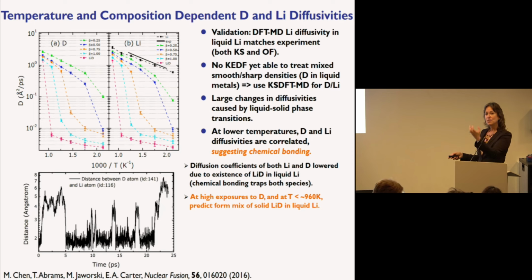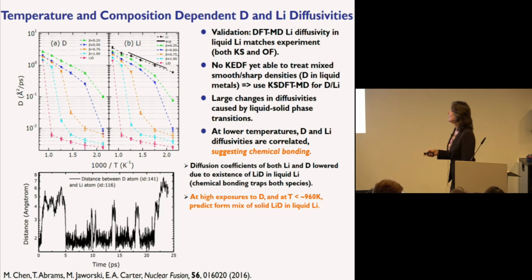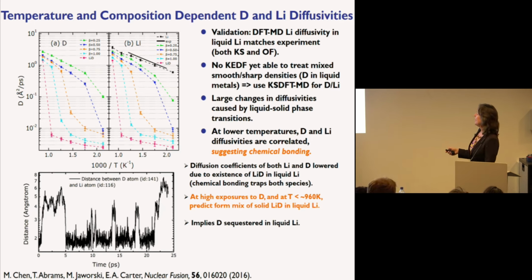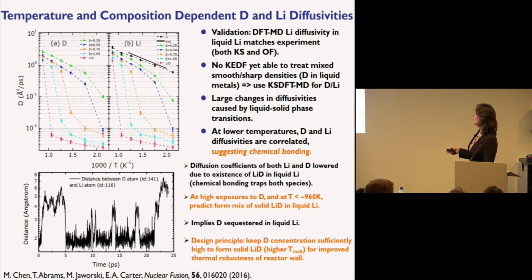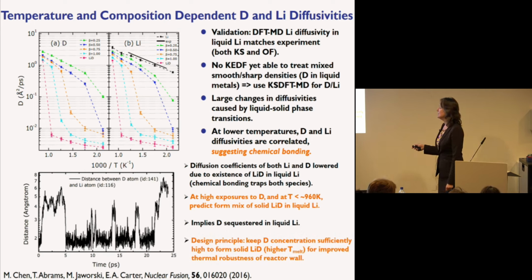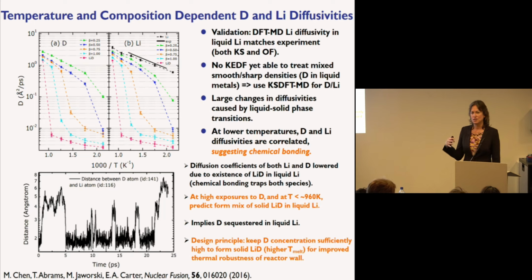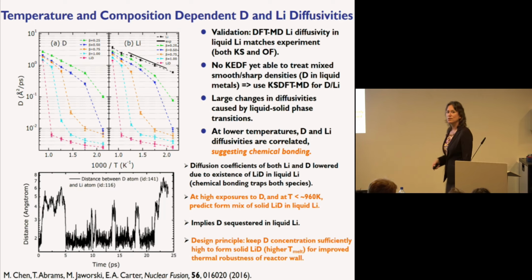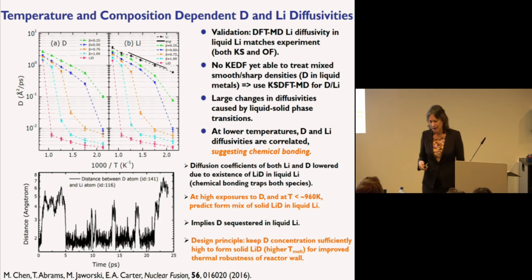And of course that'll keep the lithium present in the solution, and it implies that the deuterium is also being sequestered in liquid lithium. And so we've suggested, and the experimentalists are testing, the idea of essentially keeping the deuterium concentration high enough to form some mixture of solid lithium deuteride and liquid lithium to improve the thermal robustness of the reactor wall. That's what may be leading to the reactor wall having lower sputtering.